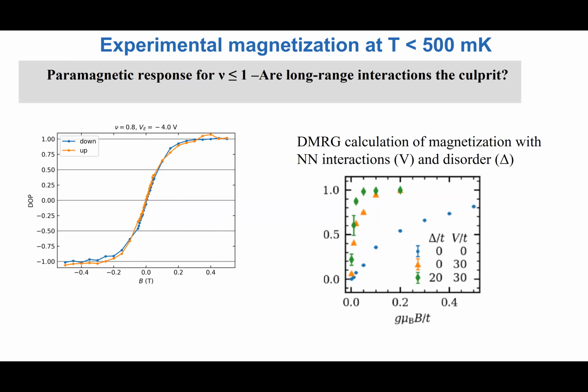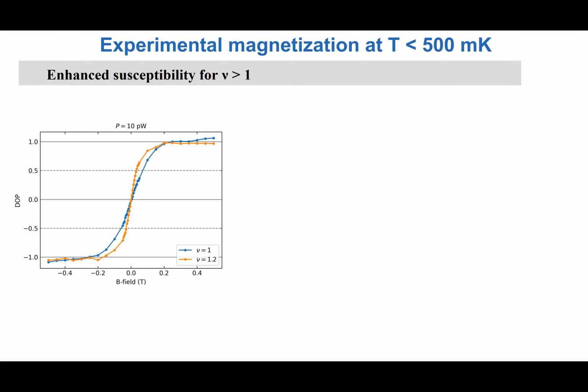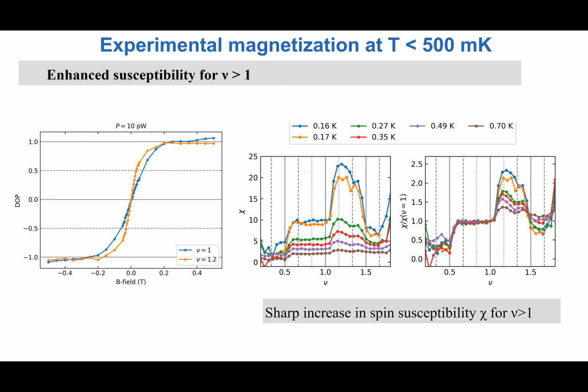One explanation that we then found is that this might be a consequence of the long-range Coulomb interactions acting together with disorder. And this is a DMRG calculation showing how the expected magnetization can become very paramagnetic-like in the presence of long range interactions. Okay, so for nu larger than one, the magnetization does pick up, as shown here. And when we plot the overall spin susceptibility, which is the main result, you can look at it normalized to nu equals one.